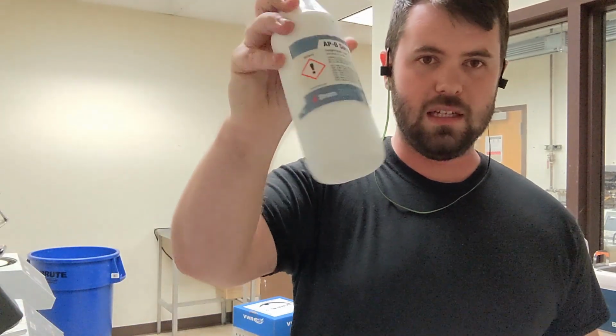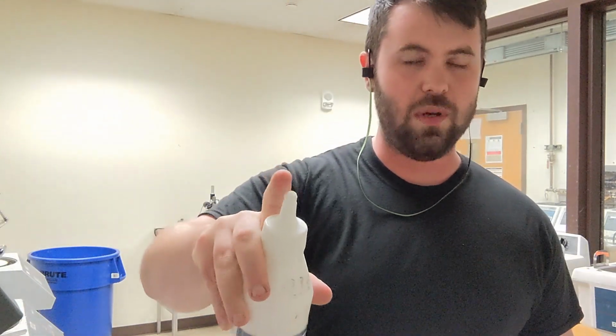I wanted to add this final little video because the 0.3 micron is really just like our final, our slight push to get it all the way to where we want it to be. So the idea behind this is you need very, very, very little. For the 6 and the 1 micron polishing stages, we used 5 to 6 little sprays of our bottle. The 0.3 comes in this little bottle like this. It doesn't really spray, it just has an open top.